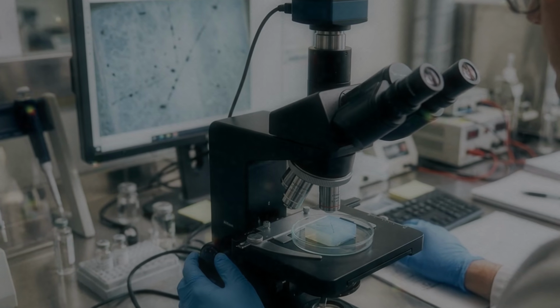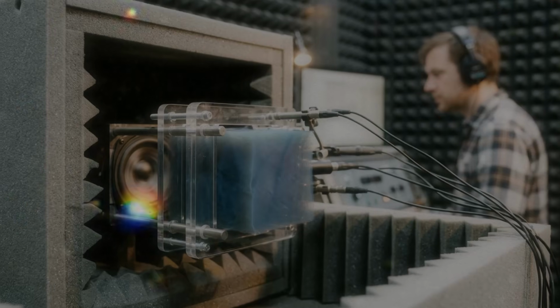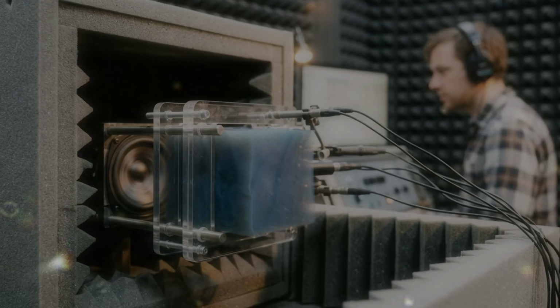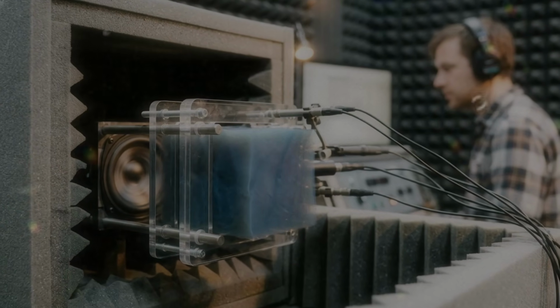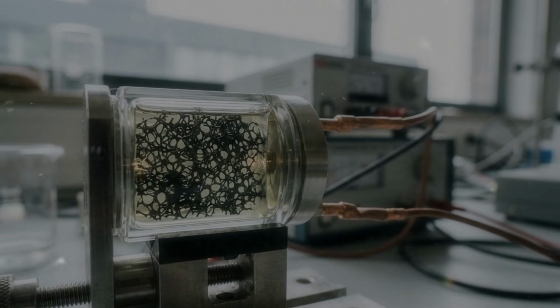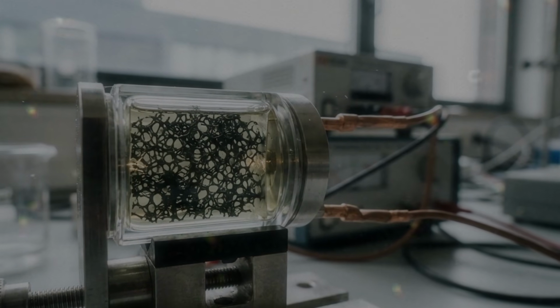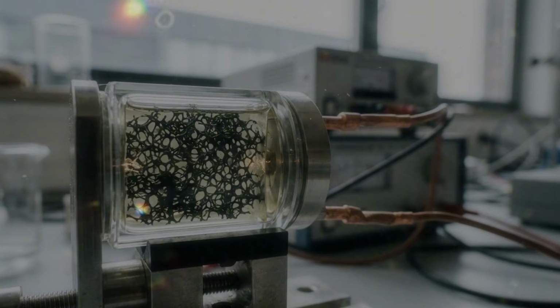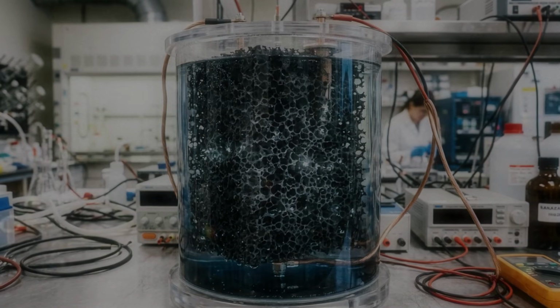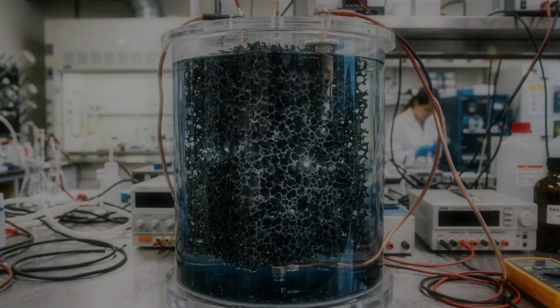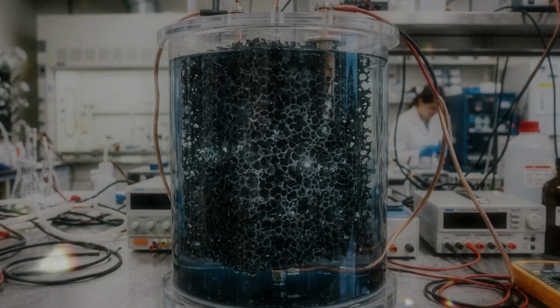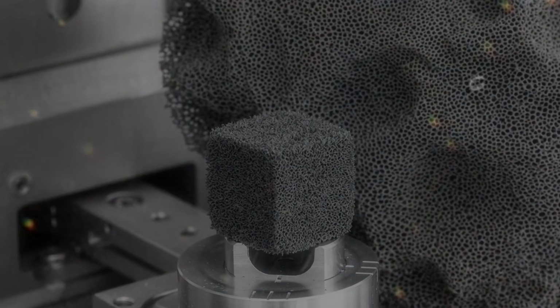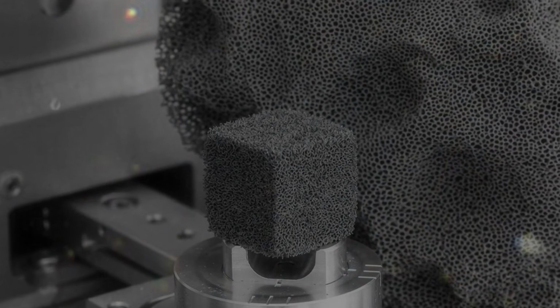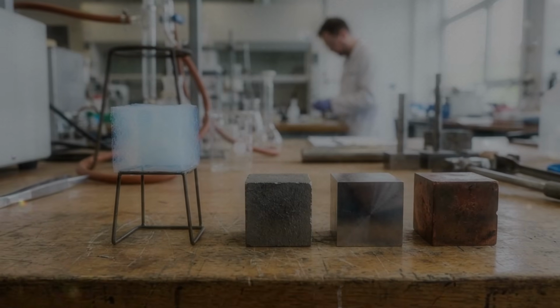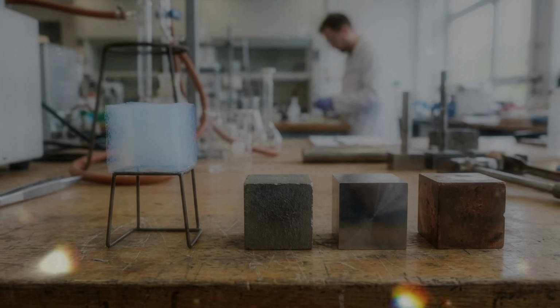The carbon sheets inside aerographene are not perfectly flat. They bend, wrinkle, and curve around open cells. These folds are useful. A completely flat sheet can lie against another sheet and stick to it. Where many sheets stack together, the structure becomes denser and loses much of its open volume. Wrinkles keep parts of the sheets apart. They create gaps and prevent complete stacking. They also allow the walls to bend under pressure. When the aerogel is squeezed, the folds can close and the sheets can buckle into the pores.